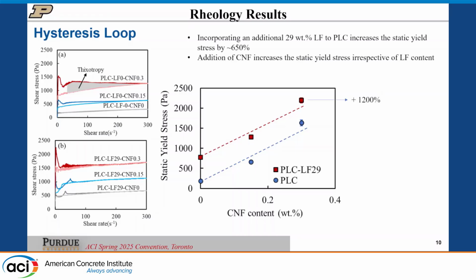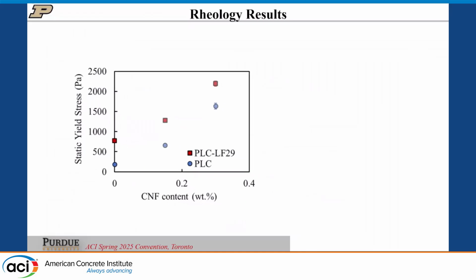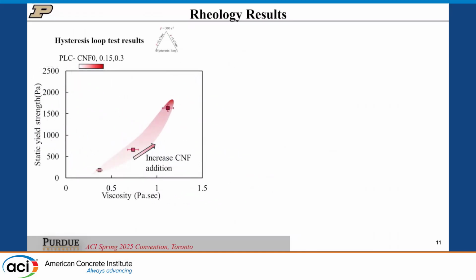With just incorporating limestone filler, we were able to gain a 650% increase in static yield stress. I'll dive deeper into the data for the mix with CNF, but overall the maximum we reached was 1200%, which is very significant for such a low content of binder.